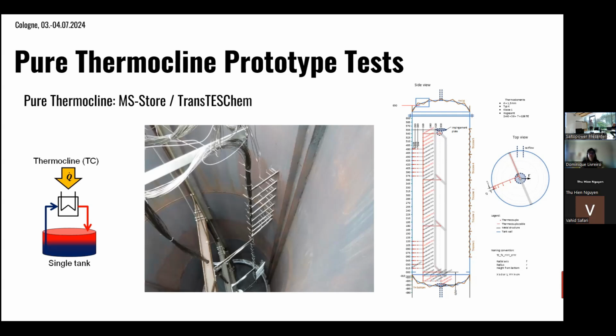So to test it, we have what we call a thermocouple tree. It's a metal structure you can insert into the tank, and you can attach thermocouples to it. And then you have the possibility, for example, to measure actual temperatures. But what we did here, because in this experiment we were less interested in the thermocline itself, it was more focusing on the near wall temperature field inside the tank. Therefore we had a two-dimensional field of thermocouples in this region.